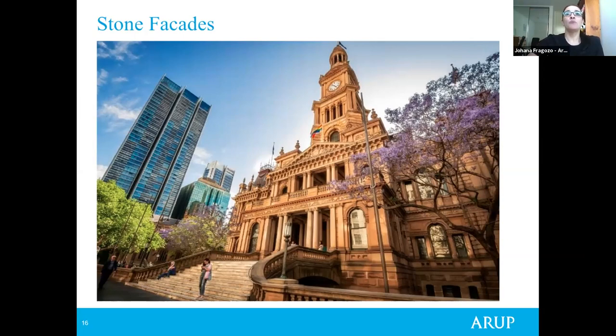We could have displacement or bulging of stone panels, and this could be due to failure or loosening of anchorage, sliding of stone off horizontal supports, movement of underlying systems such as frame shortening, or expansion due to corrosion products built up between the masonry backup material, or the steel support structure, and the face panels. Something else to consider is that when stone elements carry vertical loads from above, the condition can lead to buckling failure.